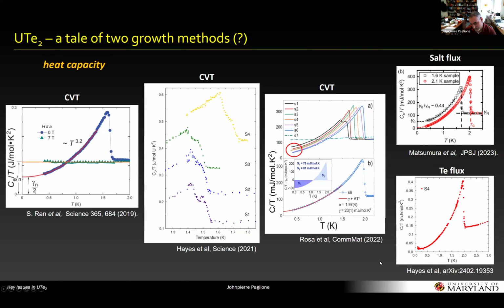And as far as I'm concerned, this is unsolved. There is probably some component of a nuclear quadrupole Schottky giving you an upturn, but it's not completely consistent with that. For instance, if you actually try to fit that data and get a splitting, the splitting is, I think, something like 50, I forget exactly, 50 or 100 millikelvin. It's quite large. It's too large to be a nuclear Schottky alone. So I don't think that affects the fact that this is definitely going down, but there's some physics down there